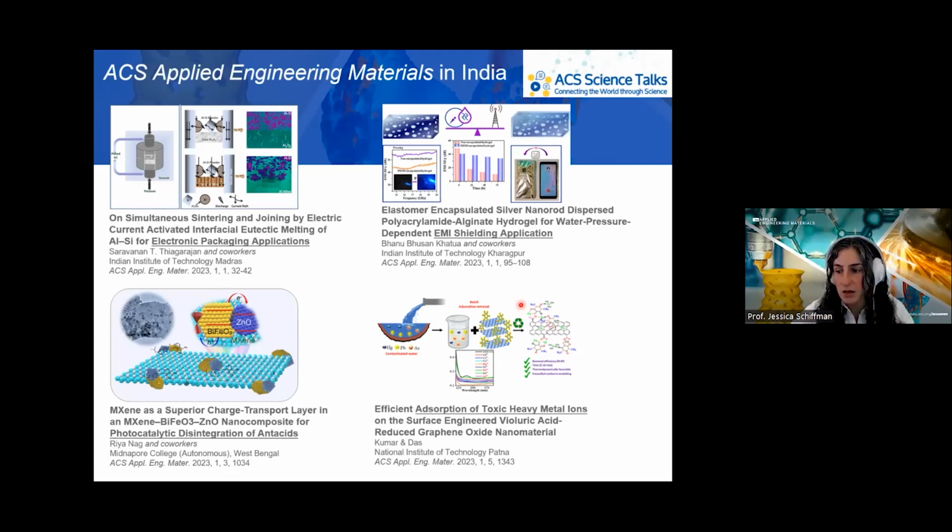We have made some surfaces with metal ions, such as silver. We have one paper where we actually electrospun cellulose nanofibers and grew zeolites on the surface, and the zeolites delivered single ions of silver. It was really an elegant paper that we were quite proud of. So the metal ions are very effective at killing bacteria, especially the single ions diffusing. When they're able to diffuse through the membranes of the bacteria, they can kill.